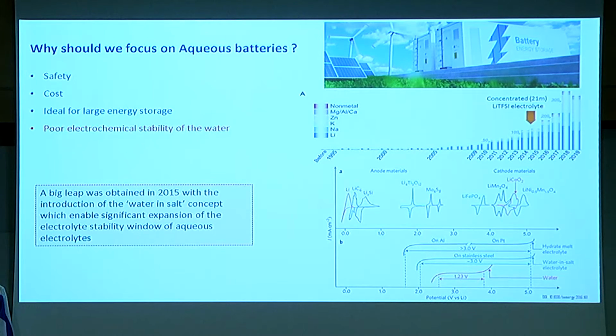So for this reason, for many years, you can see here the publication about the aqueous battery. Since the invention or commercialization of the lithium-ion battery, there are not many publications, and I would say this field was quite exotic. But I think that the big leap was obtained in 2015 with the publication of the water-in-salt concept. Water-in-salt means to use highly concentrated aqueous electrolyte, and as you can see here, you can get much wider electrochemical window from 1.23 to 3 volt and more than 3 volt by using aqueous concentrated electrolyte.